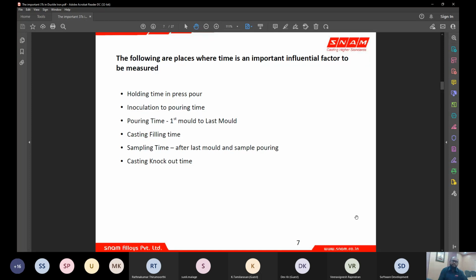So your entire 3 minutes of inoculated metal and the potency which is developed in that entire 3 minutes is lost. So there is a dwell time where the inoculant has to react and start giving nuclei. That will happen in microseconds. And if we delay any further, the extra time we take before pouring after inoculation is a loss to us. So foundries should have a control and a measure and should have a practice of pouring immediately or very close after inoculation.